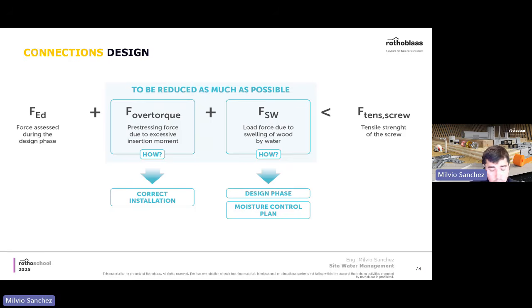During the design phase, currently the design load is always calculated in a way that it has to be lower than the tensile strength of the screw, so the resistance of the screw. But there are two components that cannot be neglected, or they have to be reduced as much as possible, which is the over torque and swelling. So those unintended tensions have to be either included in the design or minimized as much as possible by correct installation and by a moisture control plan in action, let's say.